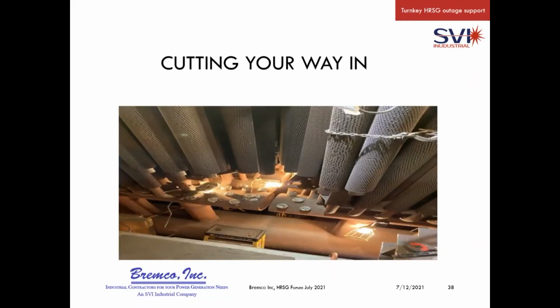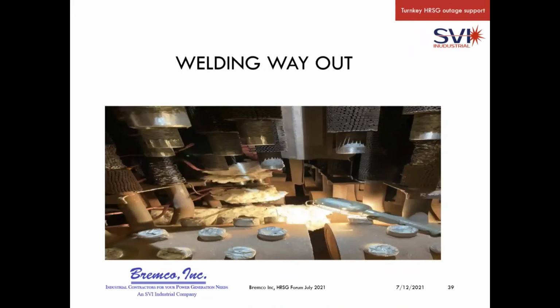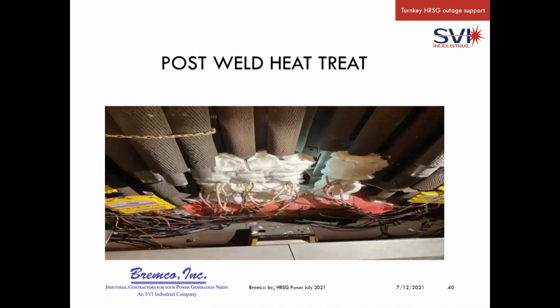Okay, here's an example of cutting your way in. On this particular unit, we had to go 6 rows deep to get to the tube repair that we had to do. And as you can see, we V'd it down so the welder can get in and make the repairs. Where it becomes even more complicated is if it's, for example, a P91 repair, where we have to wrap everything and heat treat it and keep the preheat on it. And we have to do each row. This is where it becomes very time consuming, because even though we're 6 rows in, we have to heat treat each row as we walk out, and it creates a long outage. As you can see, here's the tubes wrapped with thermocouples and doing a post-weld heat treat.